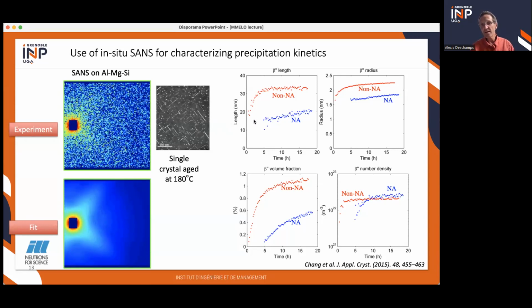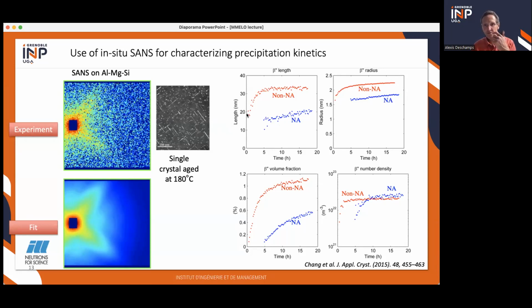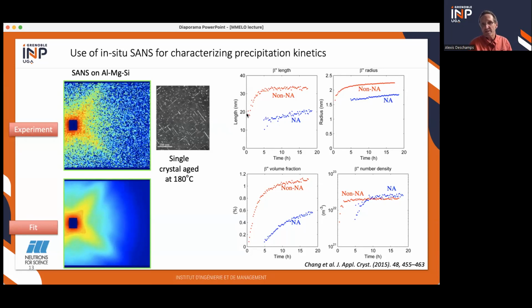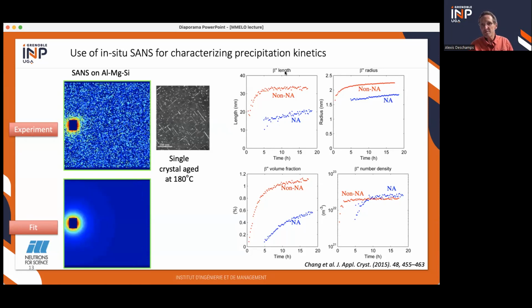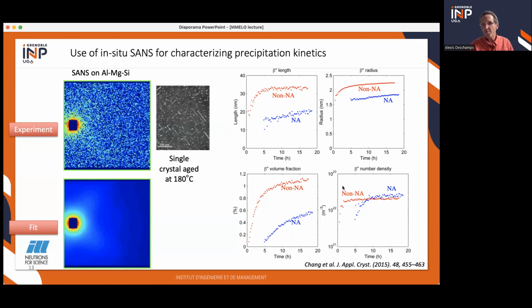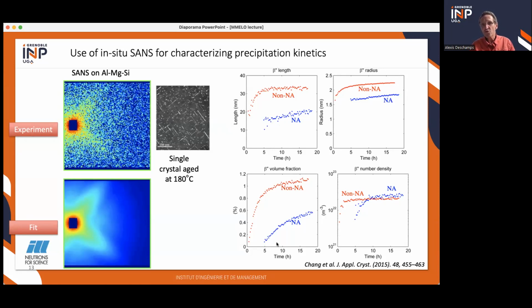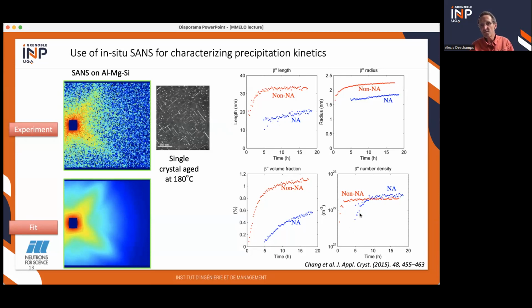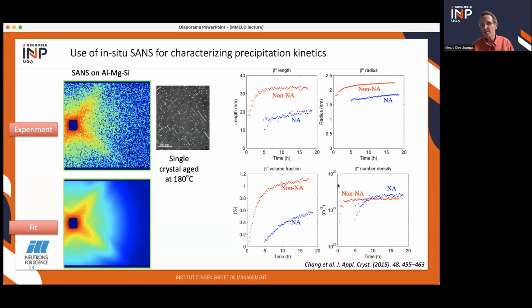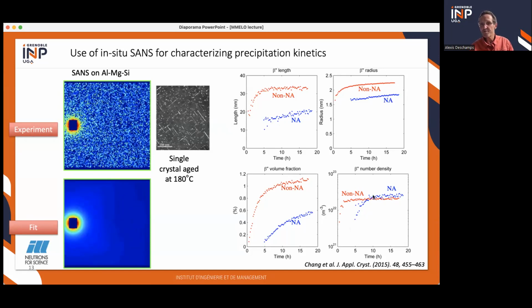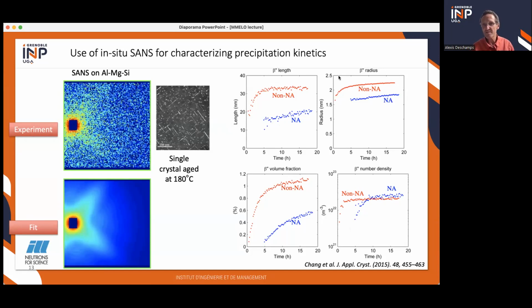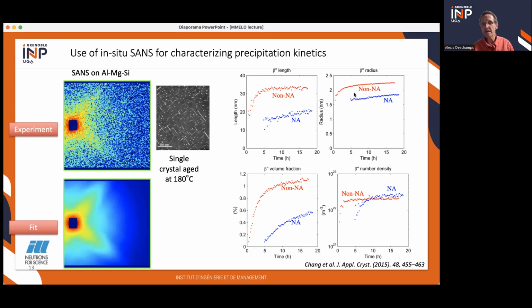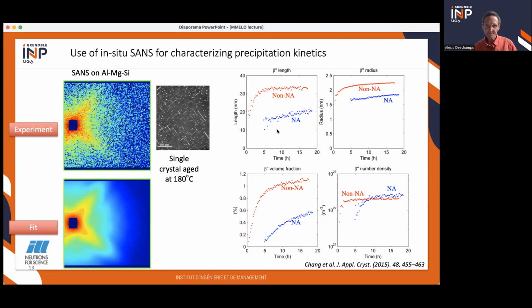And so basically, in situ, you can again get all parameters of non-isotropic particles, the length of beta double primes, their radius, their volume fraction, and number density, and show indeed that the nucleation is much faster if you don't have natural aging and much slower if you have natural aging. And that this translates also in differences in radius and length of the particles.